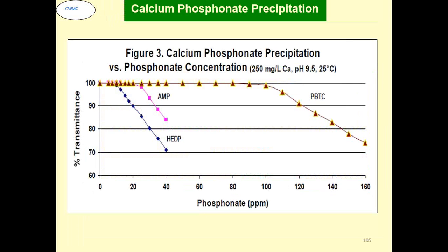Regarding calcium phosphonate, many times the treatment chemical anti-scalants like HEDP, etc., themselves mix with the calcium present in the water and form calcium phosphonate, which precipitates out. So again, that is a scale which is forming as calcium phosphonate. Among the users of this, low levels of PBTC have been found to be more suitable where there is a possibility of calcium phosphonate precipitation to occur.